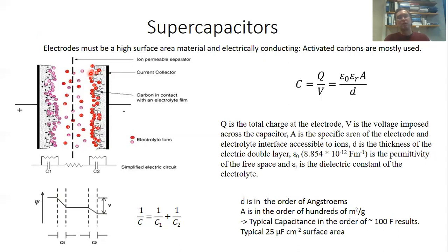So now what you form on the carbon surface is what's called an electric double layer. Layers of positive charges, which are counterbalanced by layers of anions on the pore surface, and layers of negative charges on the pore surfaces, which are counterbalanced by layers of positive ions that came out of the solution.